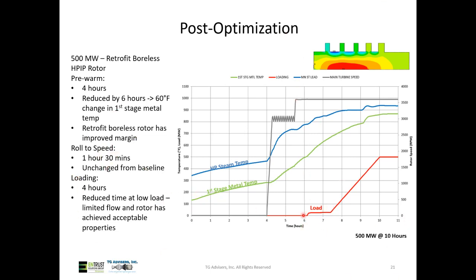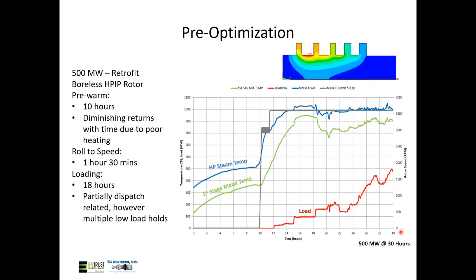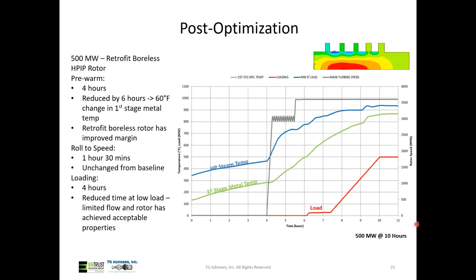And then for the loading process, we took 4 hours to get to rated load. We cut back on that low speed hold quite a bit. So really getting to 500 megawatts in 10 hours, where previously it was 30 hours. But again, some of it was driven by dispatch requirements. So even if you look at it 20 hours versus 10 hours, it's still a significant savings. And we haven't compromised the unit in any manner.